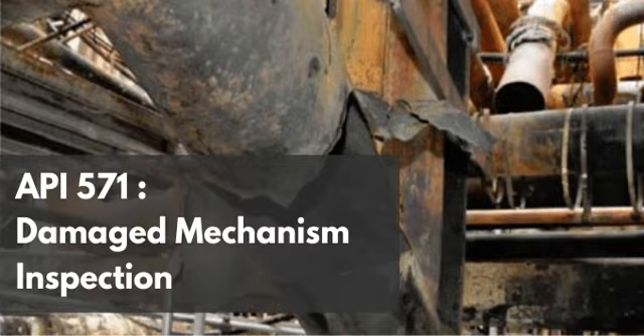But here is a catch. The environment inside these roaring pyrolysis furnaces and cokers is so aggressive, the velocities are so high, and the temperatures are so extreme that standard chromium oxides often fail. They just get blasted away. They break down, they spall off, or they get chemically stripped away by the reducing gas flow, leaving the underlying metal naked again. Which is why the data details a specific engineered solution for the most extreme environments.